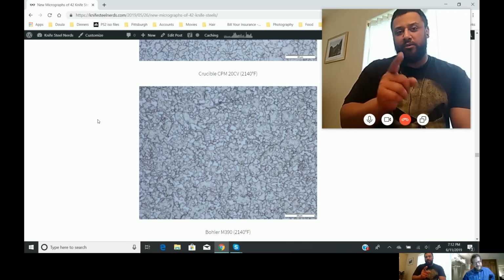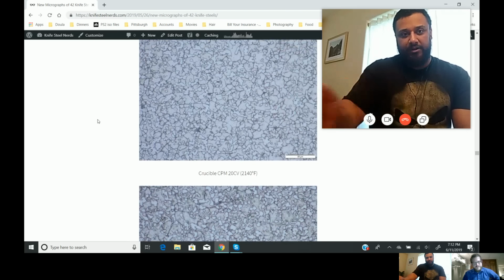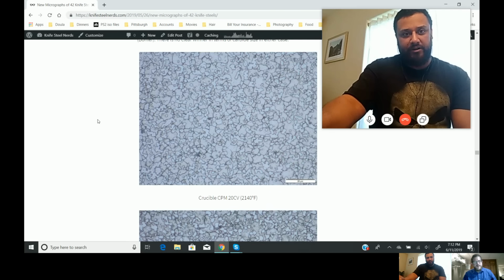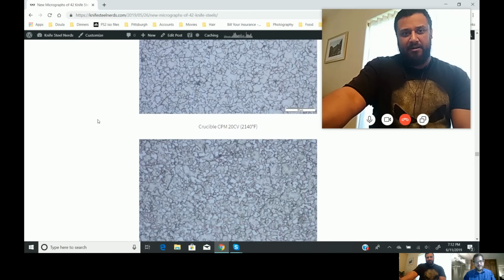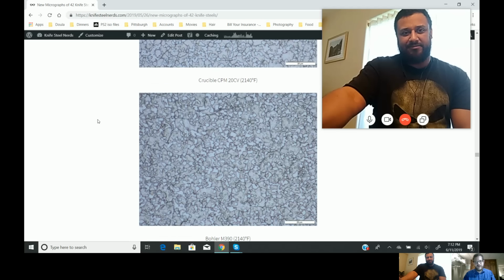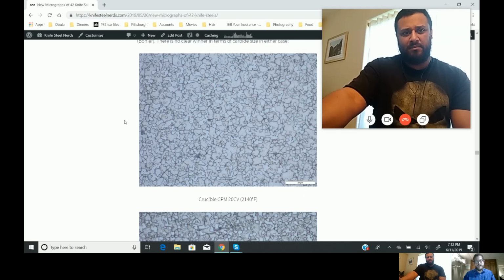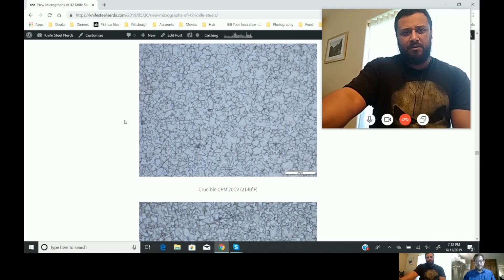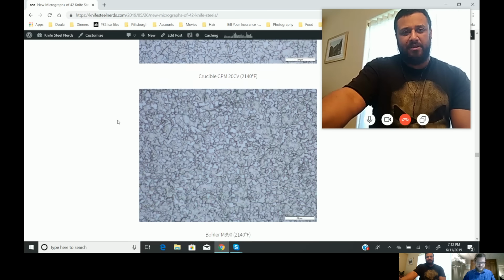Well, it wasn't the one we thought either, right? It turned out it looked like the 20CV actually had finer grain and finer carbide, just slightly, ever so slightly. Yeah, it's hard for me to make a determination. And the M390 etched slightly differently, so the carbides have stronger outlines around them, which kind of changes what it looks like. But switching to a different steel would make a much bigger difference than switching from Crucible to Bohler. They're very similar. Might as well just call them the same.